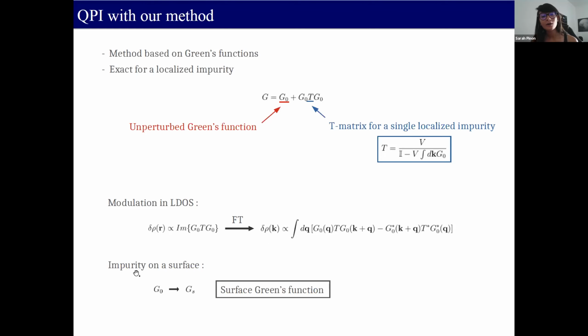In our case, we want to study a Weyl semi-metal, and we want to study the scattering of the surface states. So the G0 we consider here is actually the surface Green's function, the Green's function of the surface of the Weyl semi-metal. This is the entity we need to compute first, and it's not necessarily easy, but we found a method to compute this.